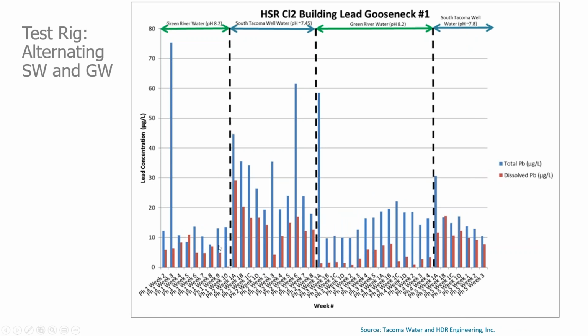Then when we switched to the groundwater at pH 7.4, as predicted, we do see an increase in lead results, both dissolved and particulate. And it takes several weeks for that to settle down. And when we always talk about it's got to re-equilibrate, what we're talking about when there's chemistry changes is that it actually has to change its mineral structure. It's going from the hydrocerussite to the cerussite.